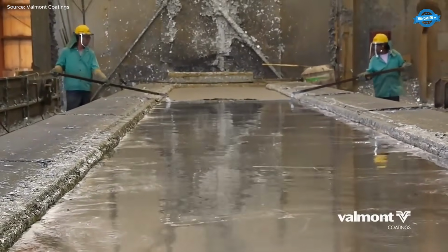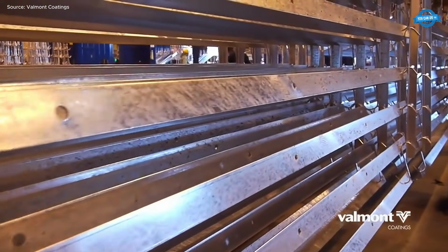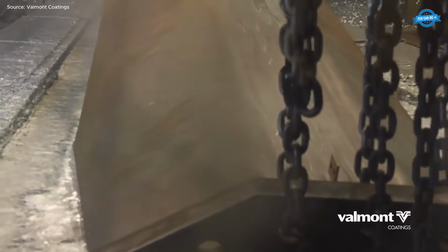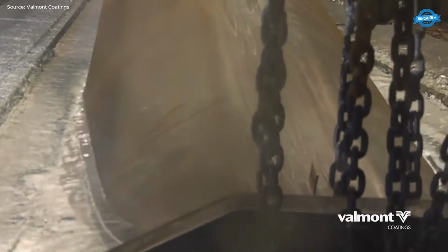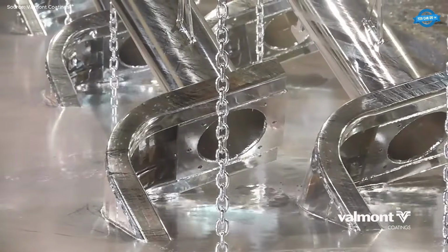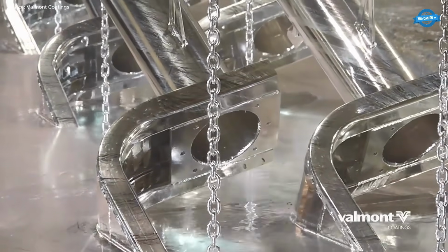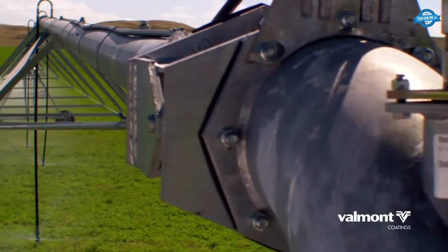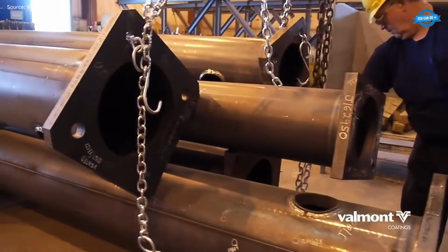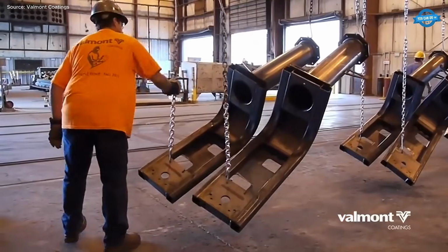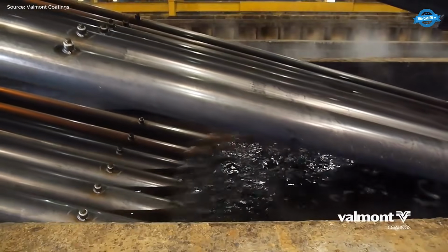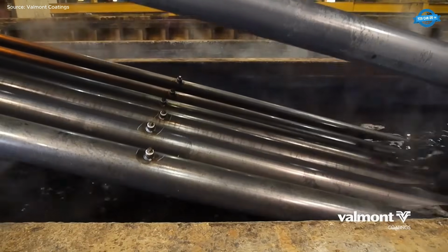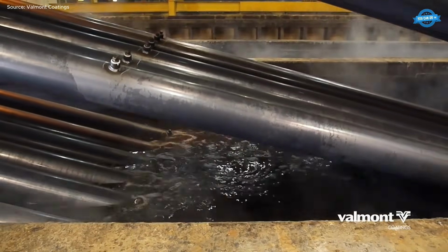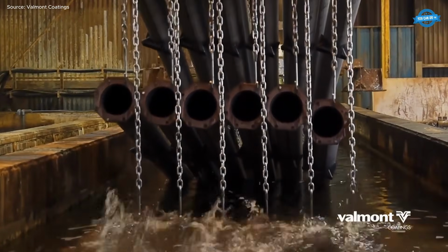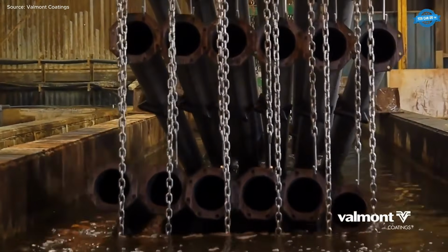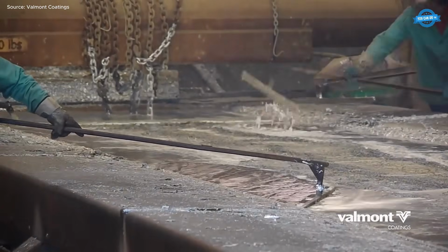This creates a series of zinc-iron alloy layers, topped by a layer of pure zinc, forming a durable, tightly bonded coating. The zinc acts as both a physical barrier and a galvanic protector, preventing rust even if the coating is scratched. Zinc also forms a stable oxide layer over time, further enhancing corrosion resistance. The process includes surface preparation, degreasing, acid pickling, and fluxing, galvanizing in a 450 degrees Celsius zinc bath, and final inspection.